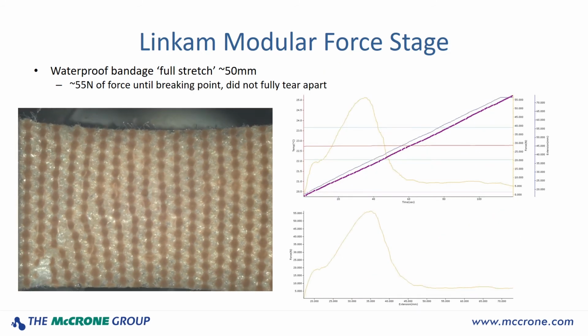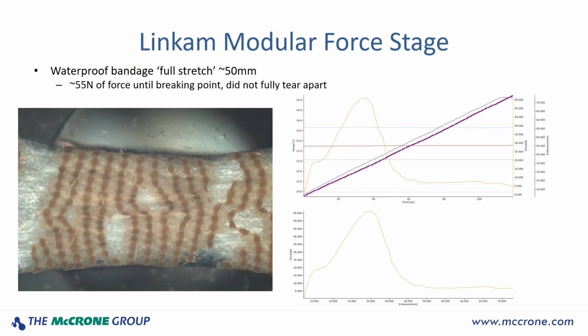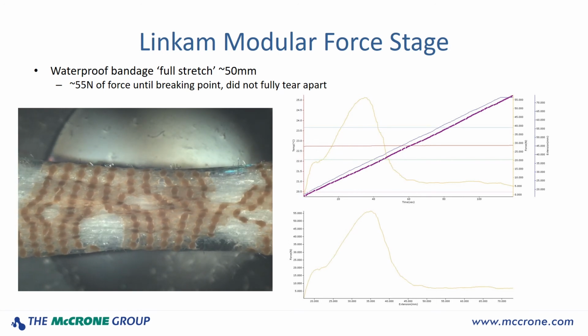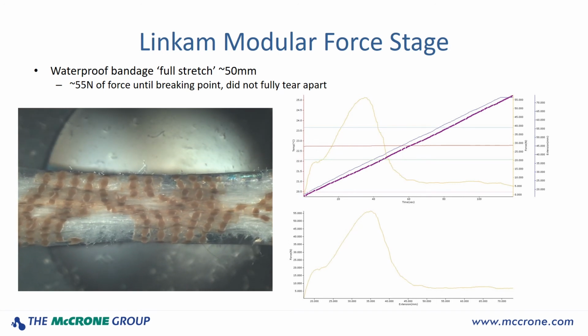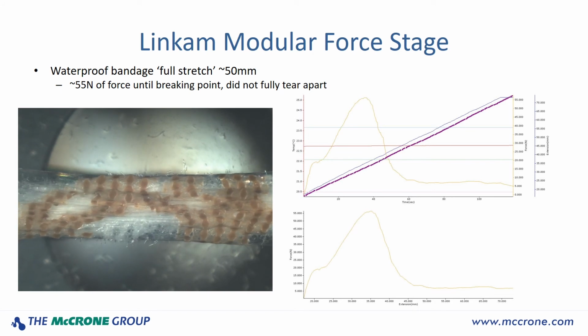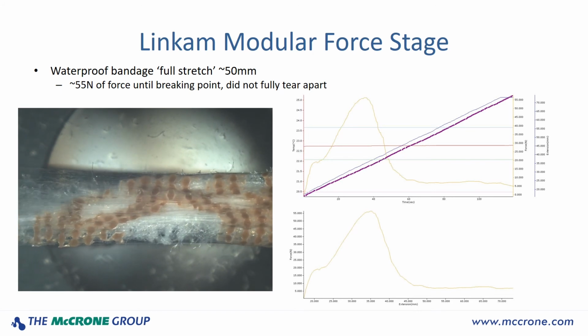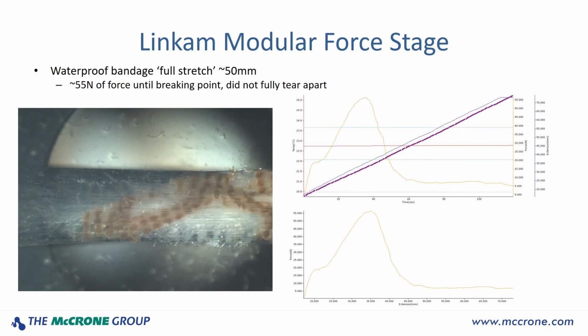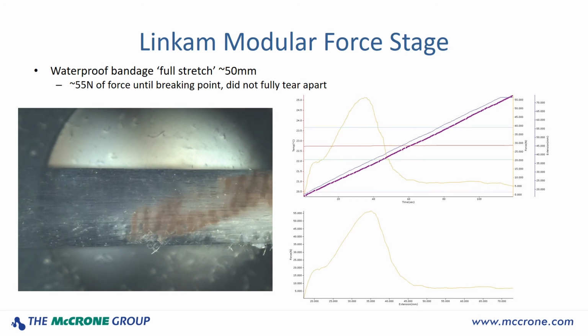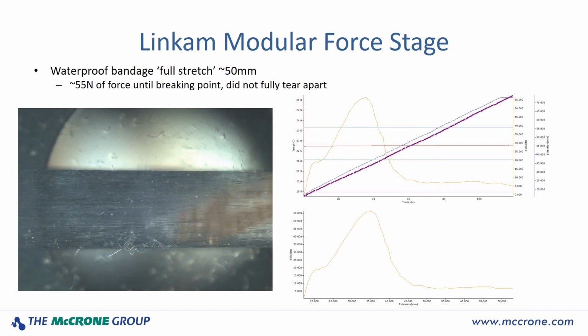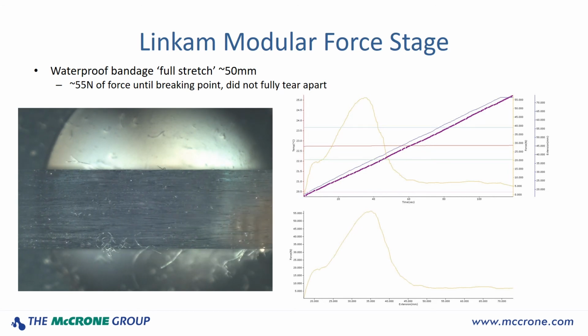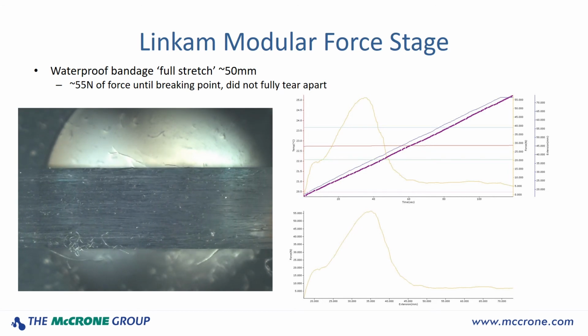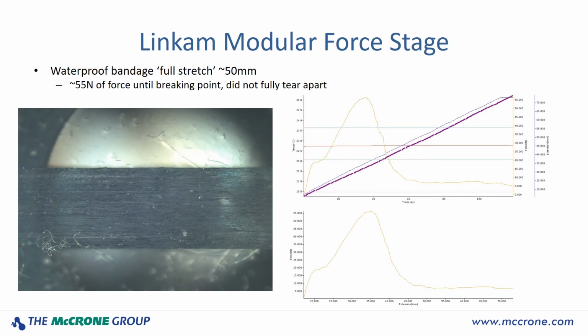The third test for the waterproof bandage was the full stretch test. I started this stretch at roughly 20 millimeters distance and ended at roughly 70 millimeters of distance, covering a full 50 millimeters of stretching distance. About 55 newtons of force was required to achieve the breaking point of this bandage, but it did not completely tear apart. There was a clear layer that stretched the most and stayed together through the entire test.